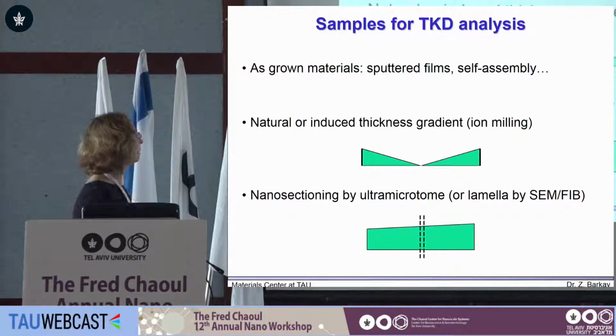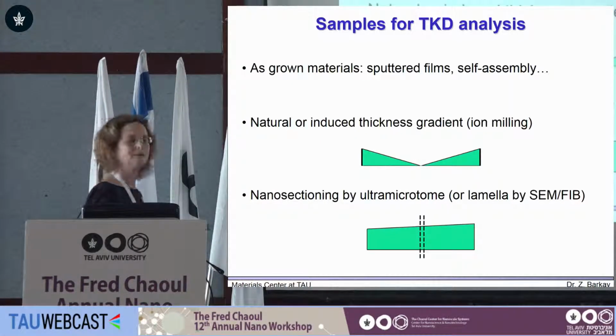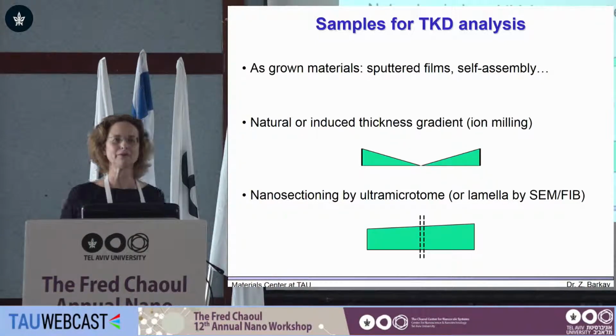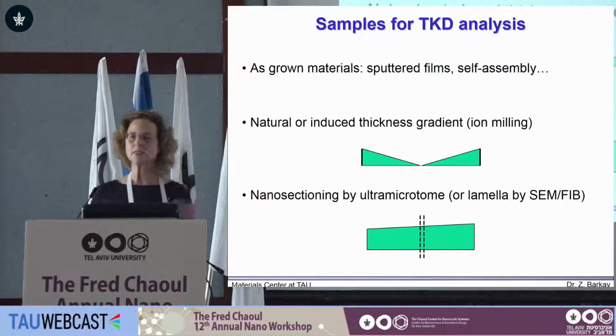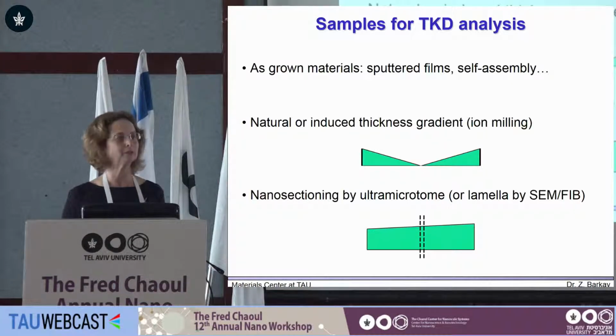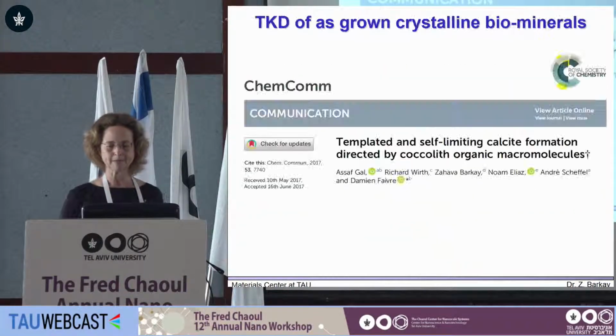So we can work with as-grown materials - this could be sputtered or self-assembly materials. We can work with natural or induced thickness gradient materials, prepared by ion milling to have a thickness gradient. Or we can work with nano-sectioned materials, by SEM FIB for those who have it, or by ultramicrotome, which was done very successfully at Tel Aviv University. I'll show all 3 types of material preparation and what was obtained for them.